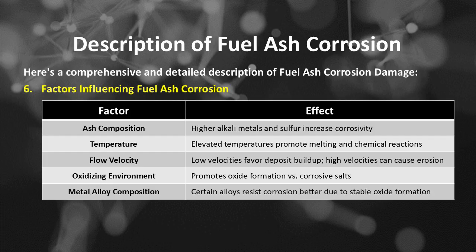If the factor is coming from temperature, the effect is elevated temperatures promote melting in chemical reactions. The third: if the factor is coming from flow velocity, the effect is low velocities favor deposit buildup, high velocities can cause erosion. The fourth: if the factor is coming from oxidizing environment, the effect is promotes oxide formation versus corrosive salts.